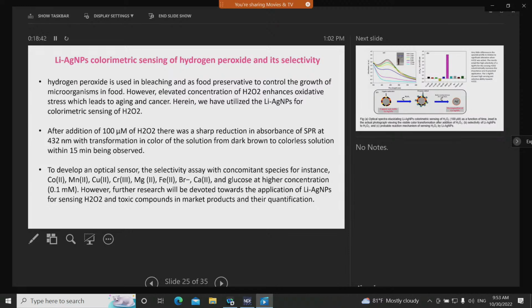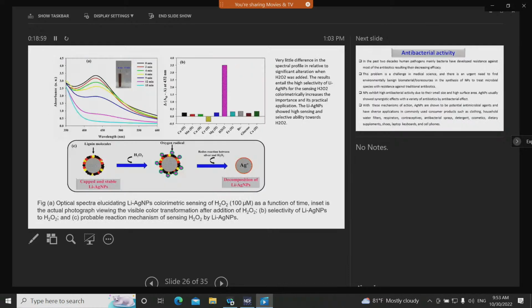And to develop an optical sensor, a selectivity assay was done, where some concomitant species, for instance cobalt, manganese, copper, chromium, magnesium, iron, bromide, calcium, and glucose at higher concentrations were used along with the H2O2. And here in this graph, we can see a very little difference in the spectral profile, related to the significant alteration when H2O2 was added. So the result indicates that high selectivity of the lignin nanoparticles for sensing H2O2 colorimetrically increases the importance and practical application. These LiAgNPs showed high sensing and selectivity ability towards the H2O2 compared with the other concomitant species.